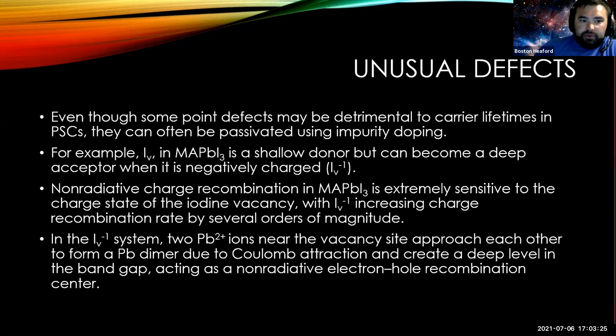Even though some of the point defects in systems can be detrimental to the carrier lifetimes, they can often be neutralized or passivated using impurity doping. For example, the iodine vacancy in the methylammonium perovskite is a shallow donor, but it can become a deep acceptor when it is negatively charged. And that creates, again, the problem of shorter carrier lifetime. The methylammonium perovskite was found to be extremely sensitive to this charge state of the iodine vacancy, with the negative one ion increasing the charge recombination rate by several orders of magnitude, which is, again, not good.